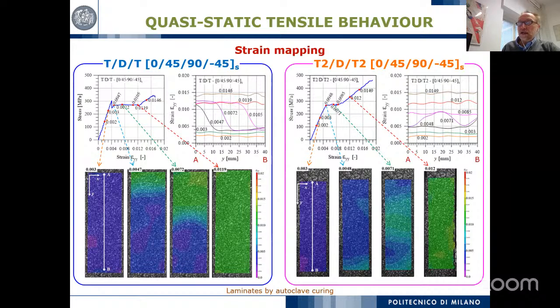In the thin ply, which I will show you also later in the modeling, you have several fragmentations and the delamination that starts at the position of the fragmentation. In this case, that is thick ply, the fragmentation starts, and then the delamination at that position starts and moves progressively through the entire model, so the entire specimen. So it's a slightly different mechanical evolution of the damage between thick ply and thin ply.